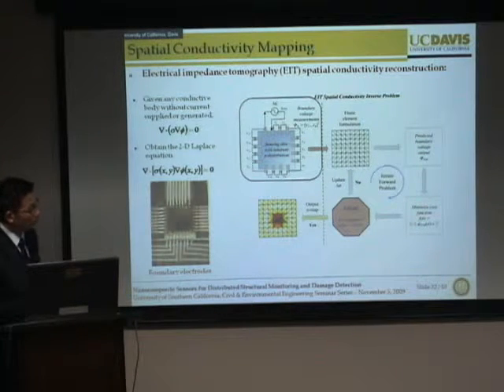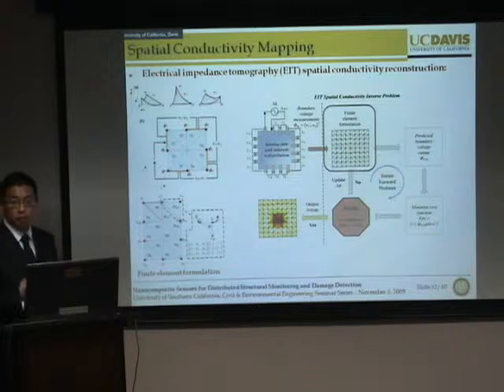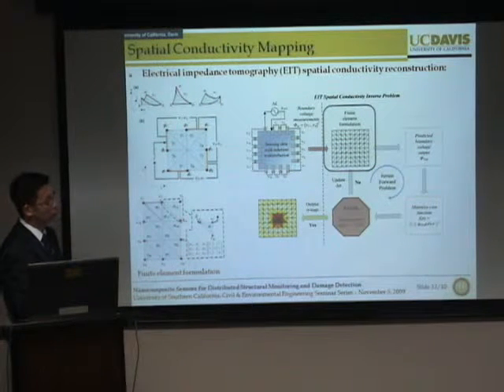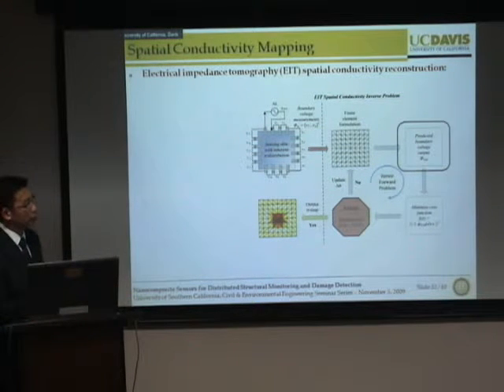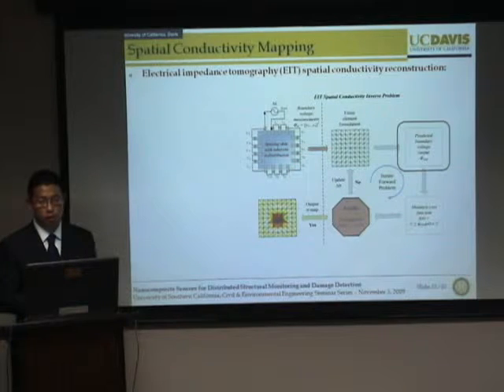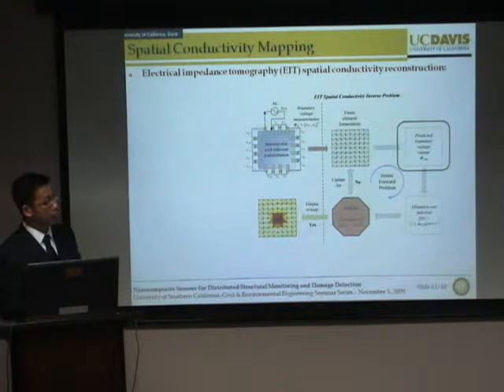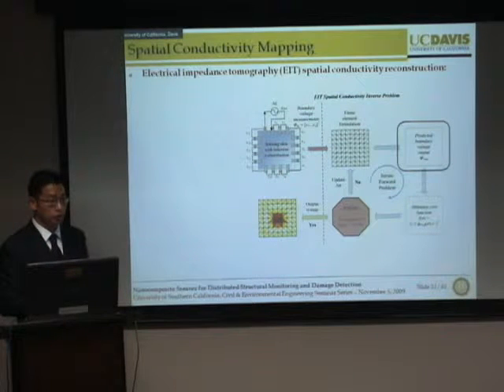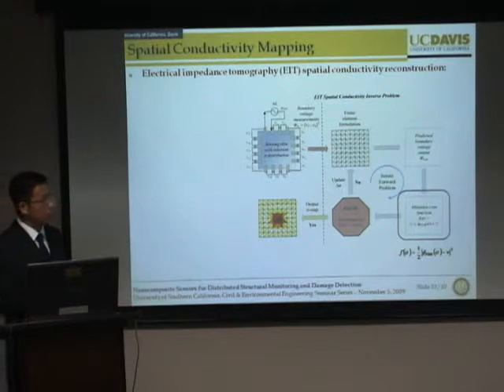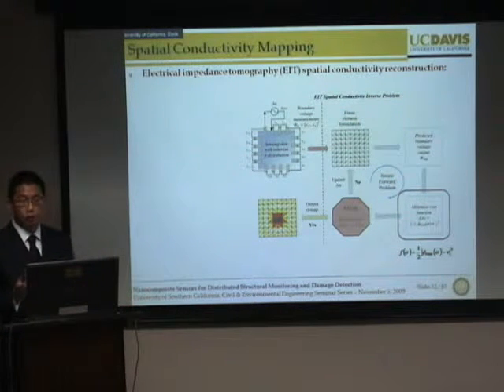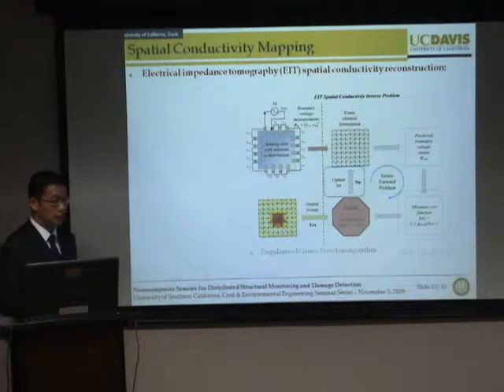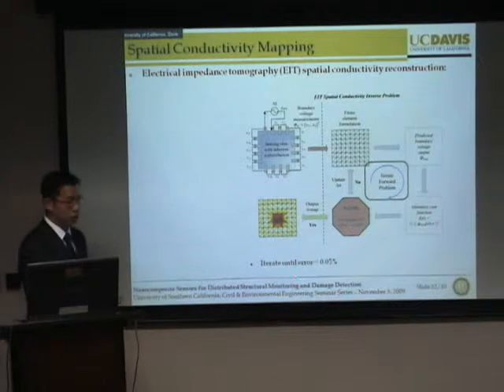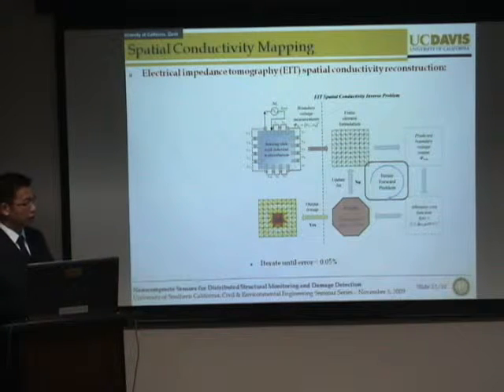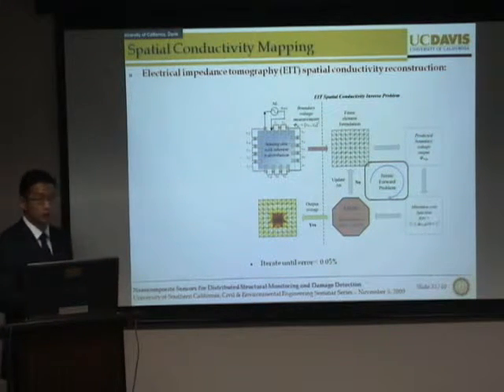So in order to achieve this goal, we can begin by relying on finite element formulation to mesh our material into individual triangular elements. We can then assume a conductivity distribution for this numerical model, apply our fictitious current to it, and predict what the boundary voltage output will be using the Laplace equation. We can then compare the predicted boundary voltage output with our actual experimental measurements, and basically iterate this process by minimizing this cost function to minimize the error between your predicted as well as experimental measurements until the error between the two is less than 0.05%.